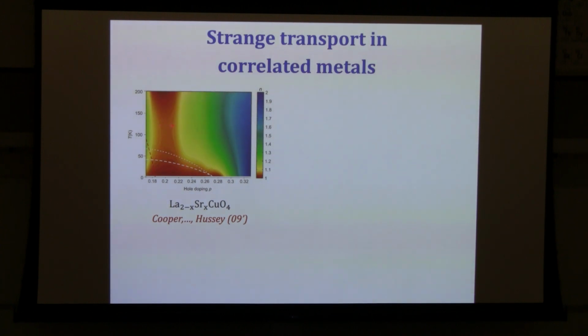At zero magnetic field, the system is actually a superconductor. This dashed white line here is the superconducting TC. So below this amount of doping, we actually can't measure the resistivity at low temperature. But what's been done in this experiment is they applied a huge magnetic field that suppresses TC sufficiently such that you can actually measure the resistivity as a function of temperature even inside what would be the superconducting phase at zero field. So they want to suppress superconductivity completely and reveal what the metallic state, which is the parent state of the superconductor, would have been like if superconductivity was somehow forbidden.